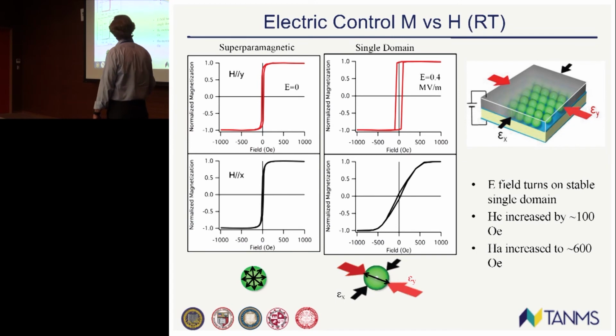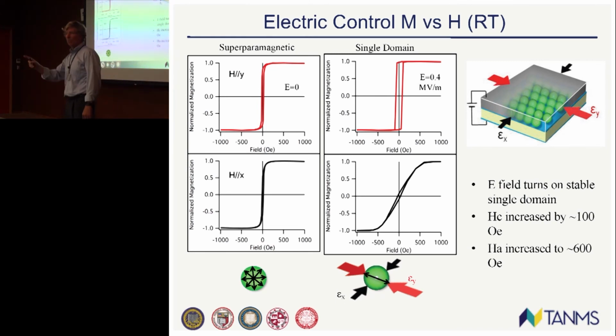M versus H curves on one sample, along the y-axis here and along the x-axis here. First of all, you will see that it's isotropic, comment number 1. Comment number 2 you're supposed to see is a lack of hysteresis. I know you see a little hysteresis there, but I'm going to show you a zero field cooling curve that shows you're right close to the blocking temperature. So this shows you have pretty much superparamagnetic behavior at room temperature.